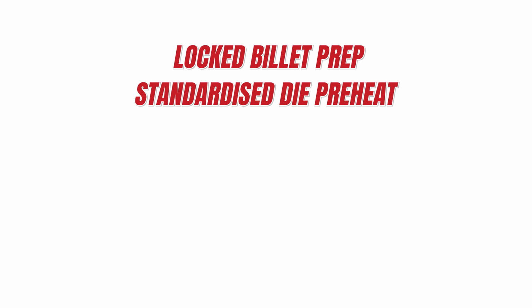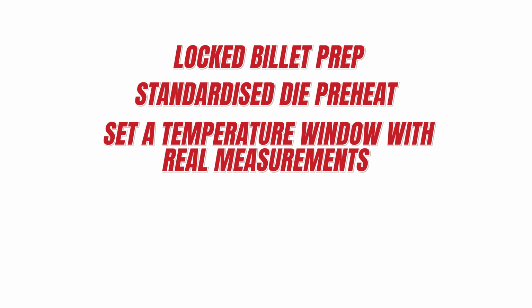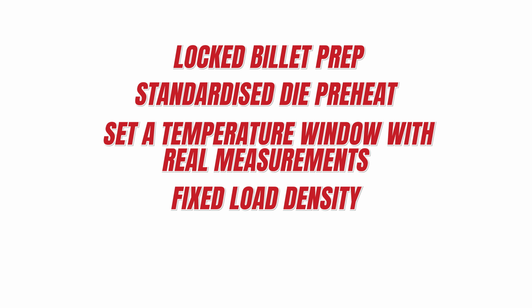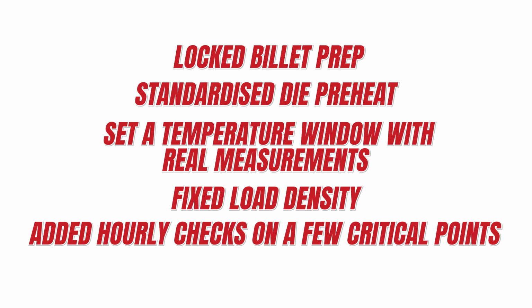I'll tell you a story. A farm equipment program had a recurring issue. A pivot pin sometimes showed fine cracks after assembly. Dimensions were okay. The root cause was mixed heat treatment behavior, with different load sizes and quench temperature drifting. We applied the 5 steps, logged the billet preparation, standardized the die preheat, set a temperature window with real measurements, fixed the load density and added hourly checks on a few critical points. The result? Stable hardness and no cracks across multiple quarters. The key was not a new machine, it was repeatable habits measured daily.